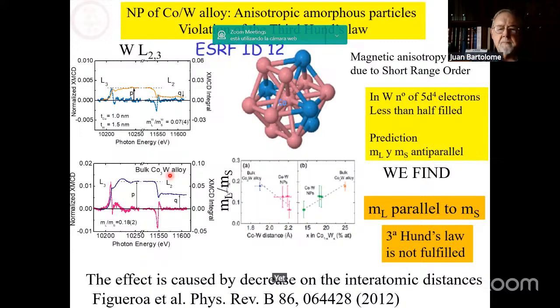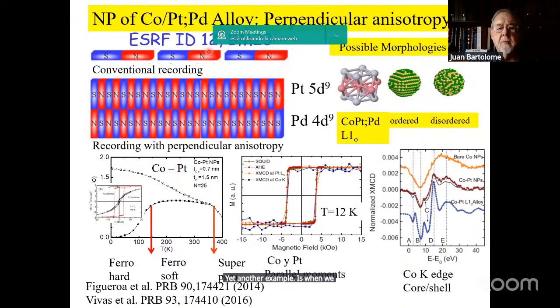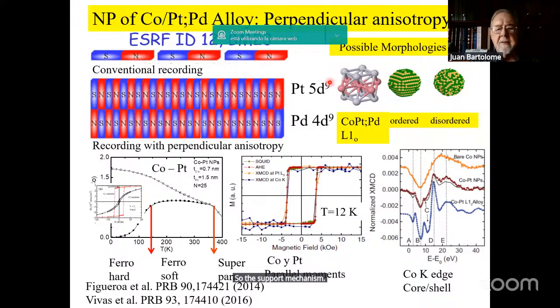Yet another example is when we sputtered platinum or palladium. Platinum or palladium have d9 bands, so they support magnetism. What's interesting is that, contrarily to the previous case, now these cobalt-platinum or cobalt-palladium alloys in the L10 structure crystallize pretty well, and they show a perpendicular anisotropy with respect to the substrate where they are deposited. This is very interesting because by using perpendicular anisotropy, we can get more dense memory supporting systems.